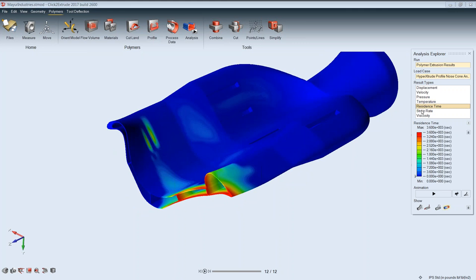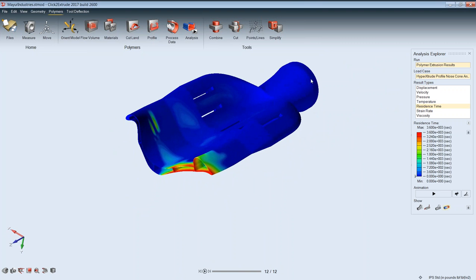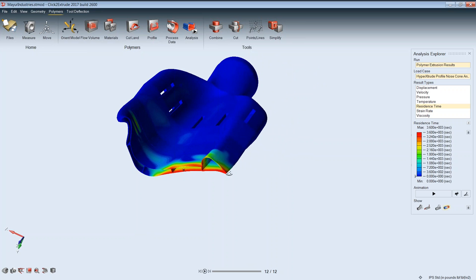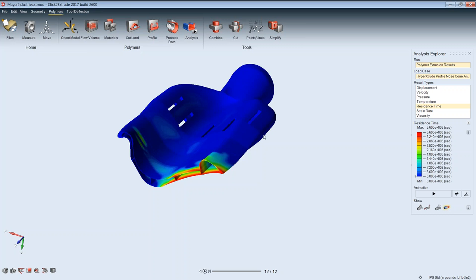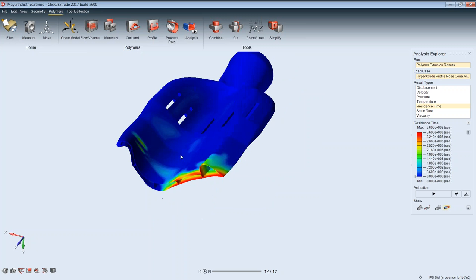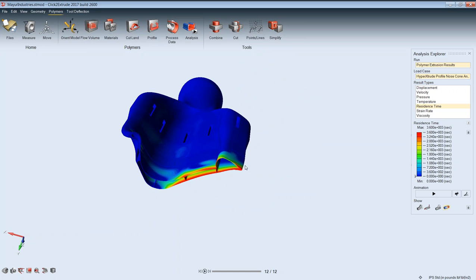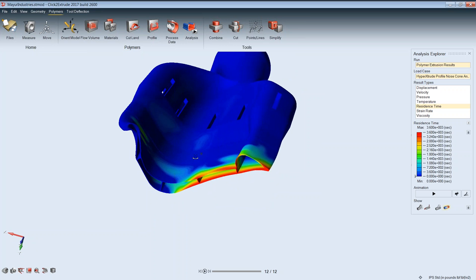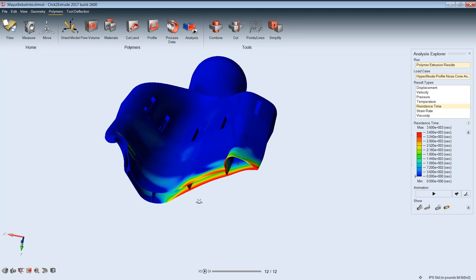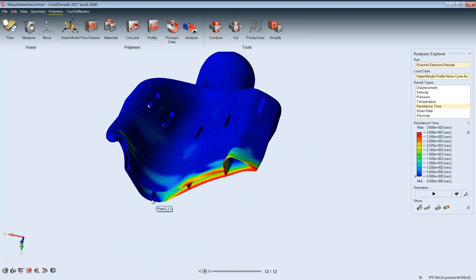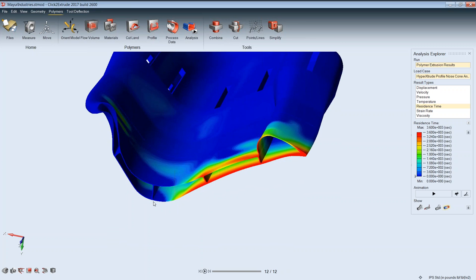Next is residence time. Residence time is if you consider any particle that's coming into the die, and it takes a certain path to reach the exit. So residence times help us to understand at which region in the die the flow is very slow, and how to rectify them. So here we can see that this region is coming out pretty slow. That is because of the thin section, and here it is less. And we need to correct the die to have a uniform or near uniform residence time at the die exit, or else we'll have some issues in the polymer.